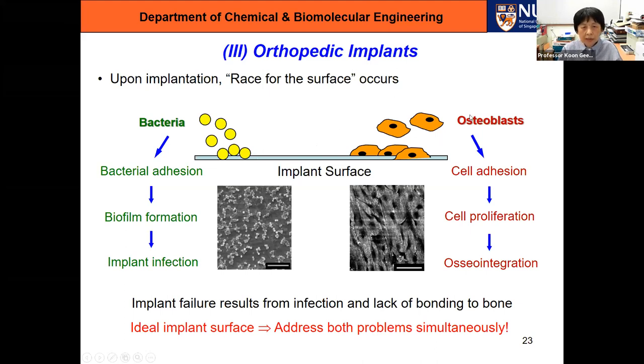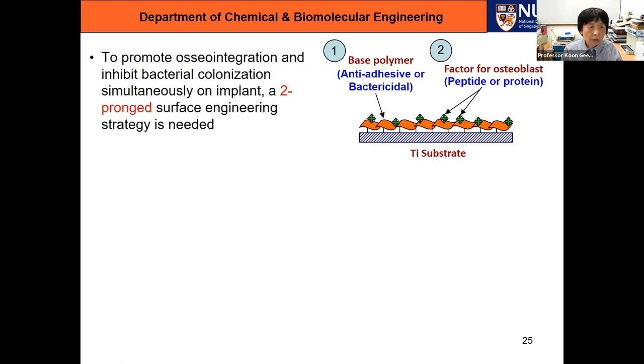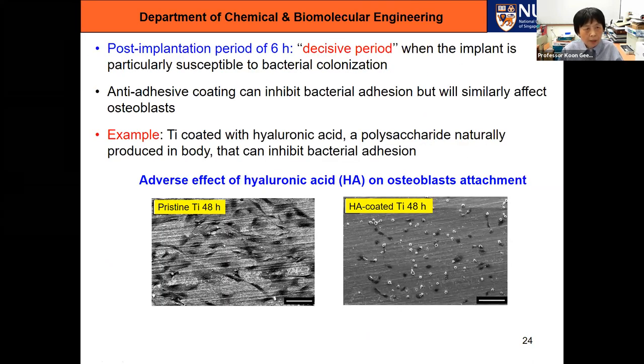So we really want the osteoblast to win, because if the osteoblast doesn't colonize the surface, there's going to be no integration with the natural bone and the implant fails. So we need to ensure that this coating that we put on the implant surface, or whatever treatment we do to the implant surface, can address both problems simultaneously: the problem of bacteria adhesion and infection, and the issue of osteointegration. The period after implantation, the first 6 hours, is deemed a decisive period, because this is when the implant is particularly susceptible to bacteria colonization.